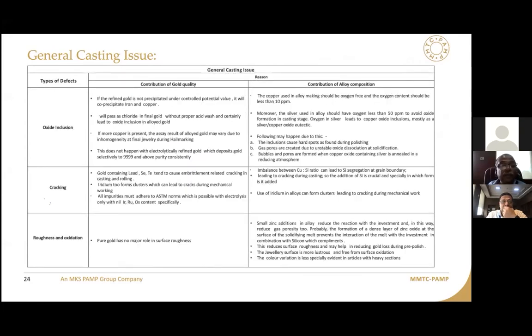The slide number 24, please. Now coming to the oxide. When you are precipitating the gold by chemical way, if your precipitation process is incorrect, you will also get copper. And that copper will pass on as chlorides and finally turn to oxides in your metal, and that oxide will get included in your cast surface. So proper controlling of this is very important when you do precipitation. Fortunately, in electrolysis this doesn't happen, and hence electrolytic gold doesn't have this.